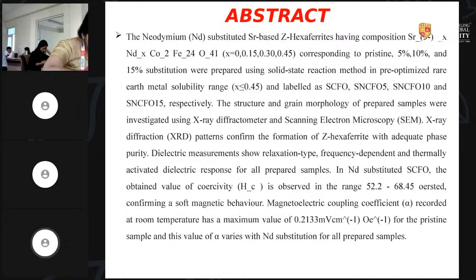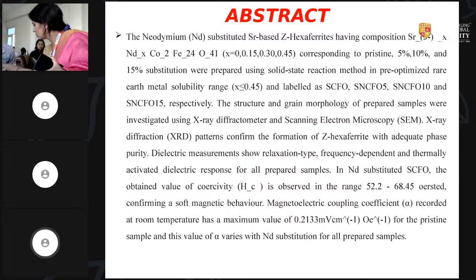Further, with the increase of neodymium in SCFO, there seems to have been no appreciable change in the peaks, which indicates that neodymium has been substituted well within the host matrix without substantial change in the structure. However, the intensity of the peaks varies with neodymium substitution. The lattice parameters corresponding to the pristine sample were obtained in our previous report on the SCFO, where only two phases, W and Z hexaferrite, were used during Rietveld refinement of the XRD data. As stated above, in the present case, no structural change is visible from the peak position of neodymium substituted samples, whereas for samples with lanthanum substitution, the onset of the structural change appears clearly in the XRD patterns.